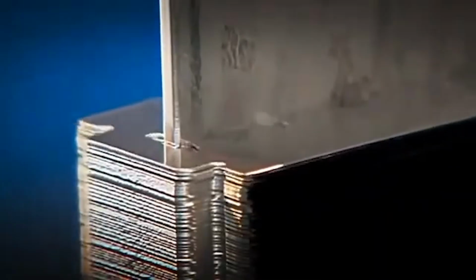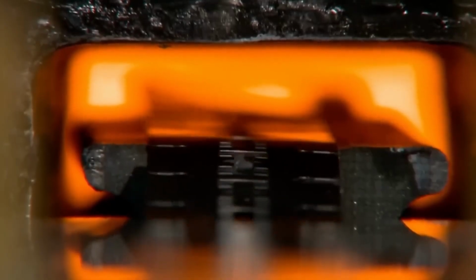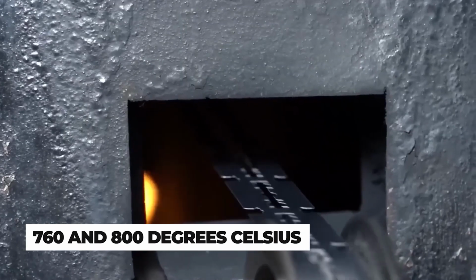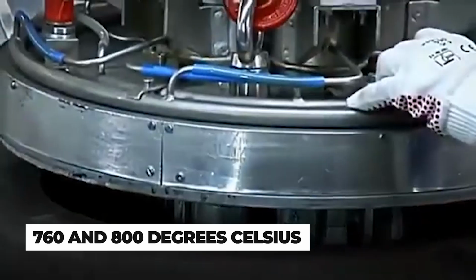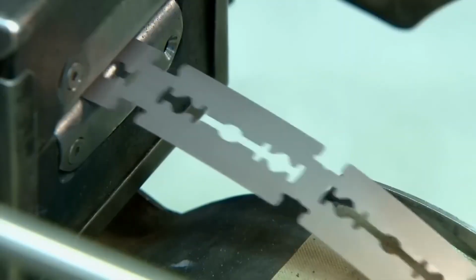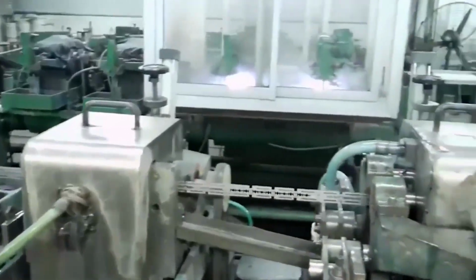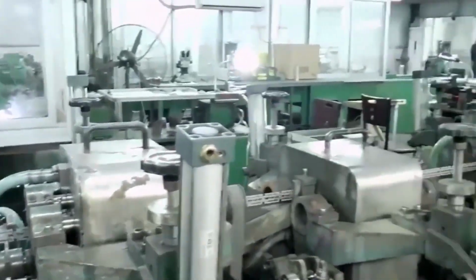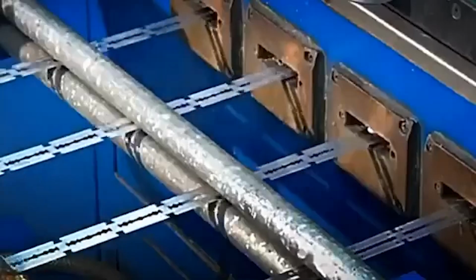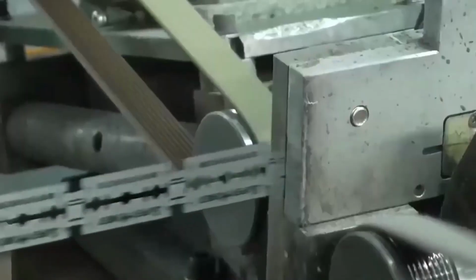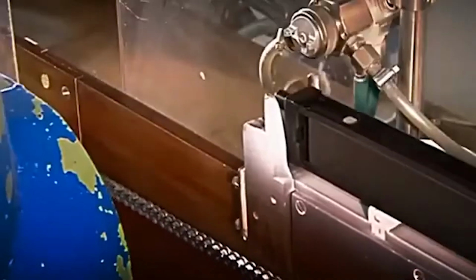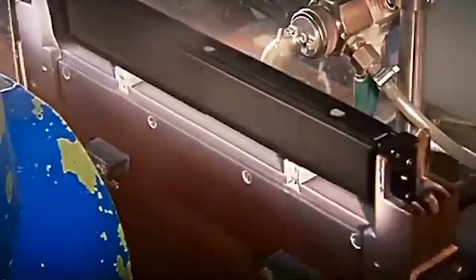Accepted blade blanks entered continuous hardening furnaces, where they were heated to temperatures between approximately 760 and 800 degrees Celsius, the range at which high-carbon steel undergoes the austenitic transformation that enables subsequent hardening. After holding at the target temperature for a controlled duration, the blanks were quenched rapidly in oil, dropping their temperature within seconds and locking the steel's internal structure into its hardened, martensitic form.